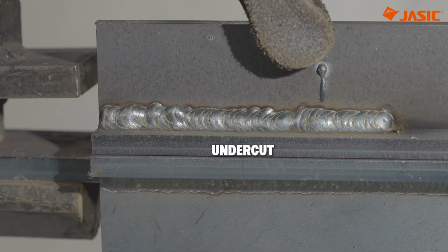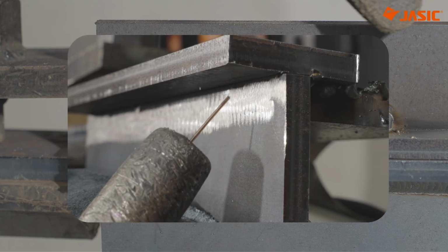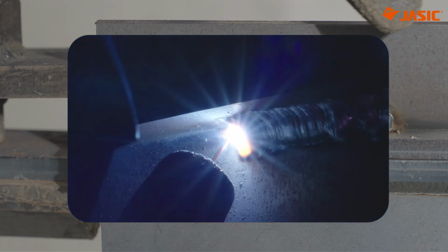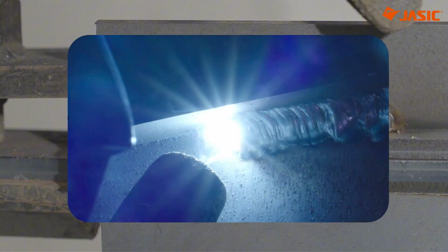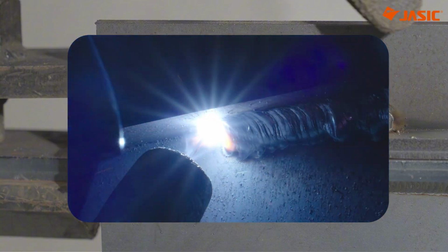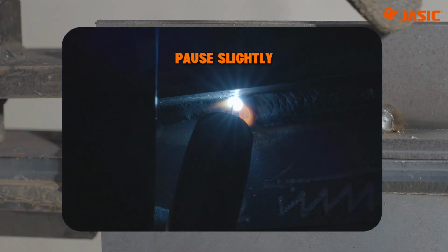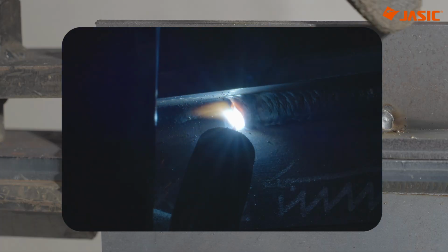You can also adjust your travel speed and movement pattern to transfer the molten pool forward more quickly. Undercut often occurs along the upper side of the joint. This can happen when you don't lower the gun enough or don't direct the arc properly toward the upper groove edge. Too much heat is concentrated along the edge without enough filler metal to fill it. When you reach the upper side, pause slightly and make sure enough filler metal is being deposited to fill the edge properly.